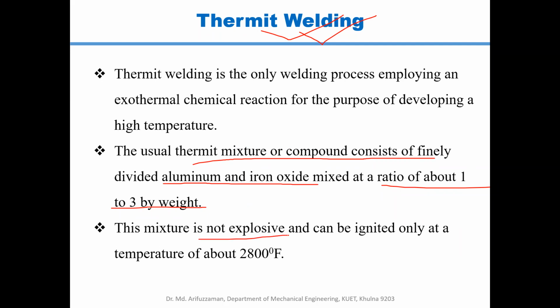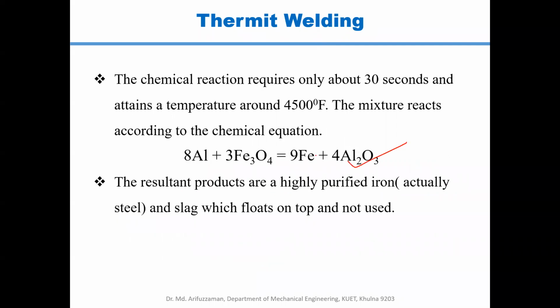Okay, the mixture is not explosive and can be ignited only at a temperature of about 2800 degrees Fahrenheit. When you raise the temperature of the thermit mixture to 2800 degrees Fahrenheit, then the aluminum and iron oxide react, and aluminum oxide is produced, leaving pure iron in the zone. And aluminum oxide has a very low density compared to iron, so aluminum oxide comes out of the liquid and accumulates on the top of the container. Okay, and the pure iron is used to conduct the welding process.